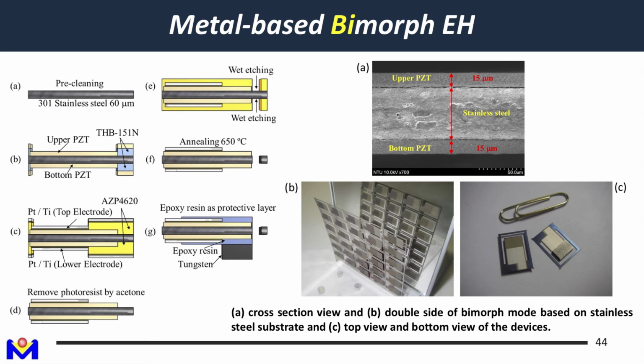The overall process is like this. We start from a 301 stainless steel substrate with a thickness of around 50 or 60 micron. With this thickness, you do not need to do the backside etch and back micromachining of a typical silicon-based transducer. So this is also one of the reasons the overall fabrication cost is much lower and simpler. And then we deposit PZT on top and use lithography to define the pattern. We can also deposit a bottom PZT to do bimorph devices. And then we use platinum and titanium as the top electrode and bottom electrode.